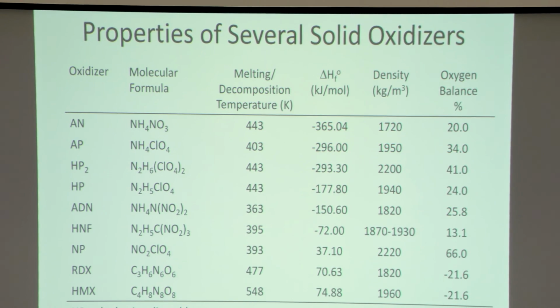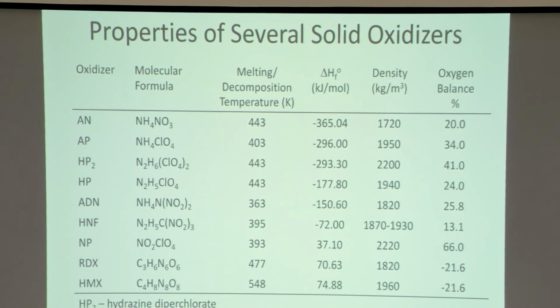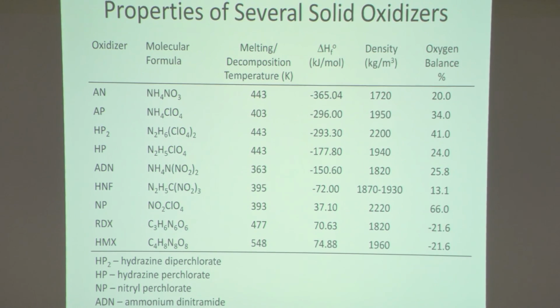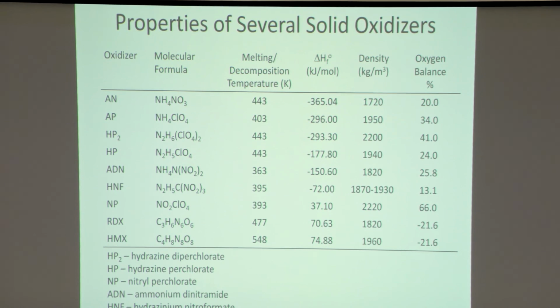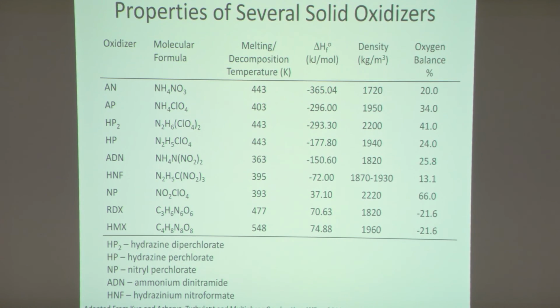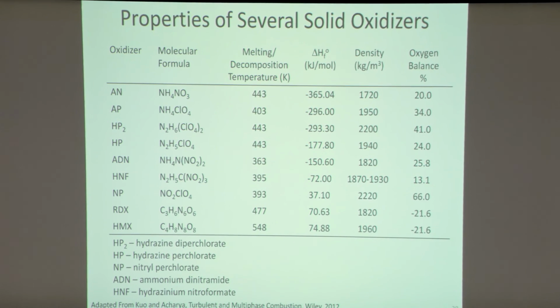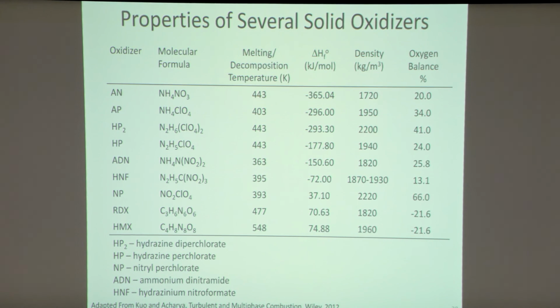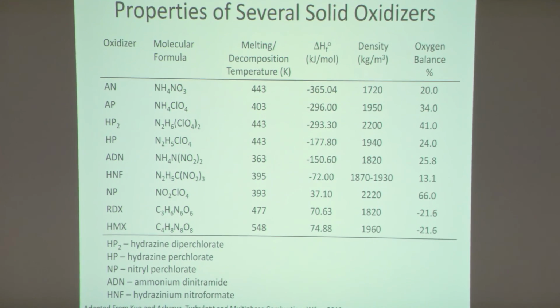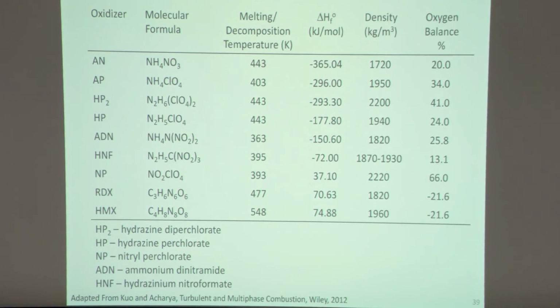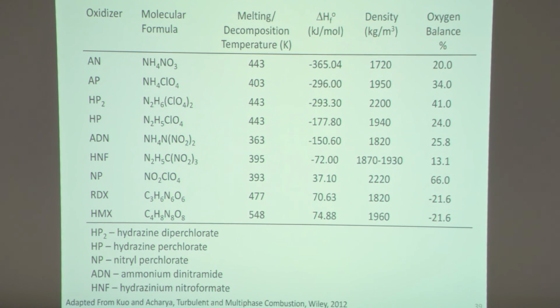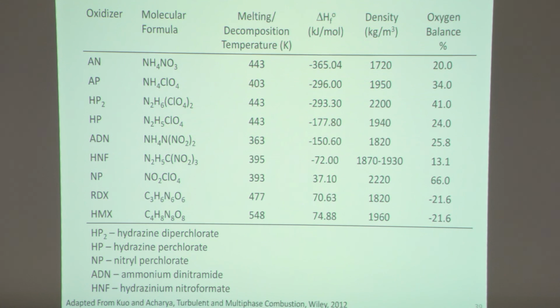Okay, here's some properties of several solid oxidizers. So I list here ammonium nitrate, ammonium perchlorate, hydrazine diperchlorate, hydrazine perchlorate, ADN, ammonium dinitramide, hydrazinium nitroformate, nitryl perchlorate, RDX, and HMX. Important properties are melting temperatures, obviously their heats of formation, their densities. You can see the densities here are quite a bit higher than the hydrocarbon. So remember I said the typical binder HTPB is going to have a density like 0.9 grams per cc.